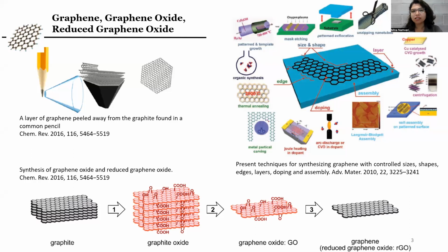First, I would like to start with a short introduction about graphene and its derivatives. High-quality single-layer graphene was first recorded by Novoselov and Geim, who pulled apart a single layer with a Scotch tape from graphite. There are various methods to prepare graphene, such as mechanical exfoliation, liquid phase exfoliation, thermal decomposition of carbon, silicon carbides, and CVD. It has excellent mechanical, thermal, optical, and electric properties. The zero band gap of graphene gives it excellent electron mobility, but for the same reason, functionalization cannot happen on the surface.